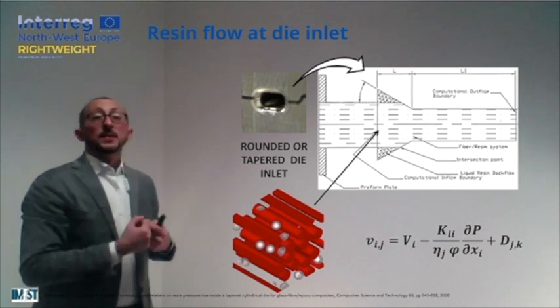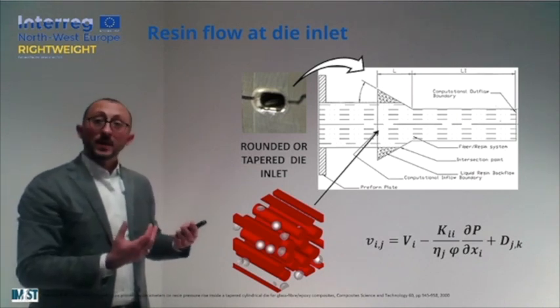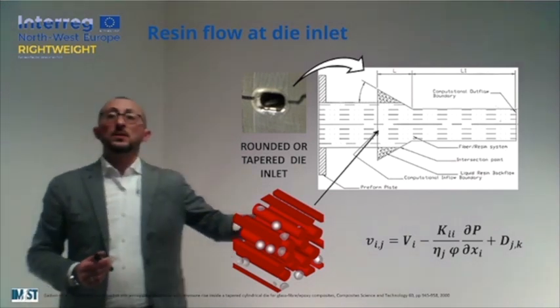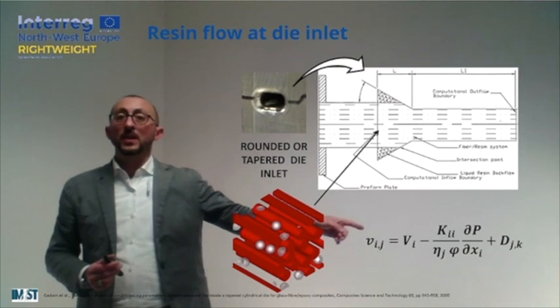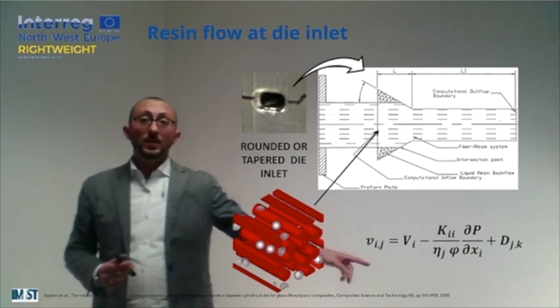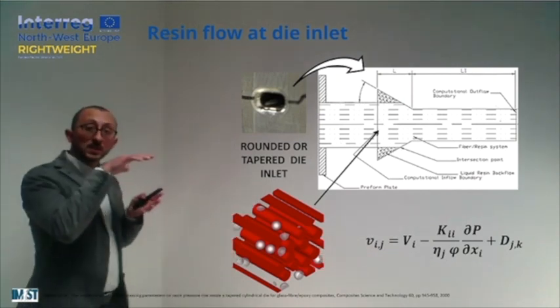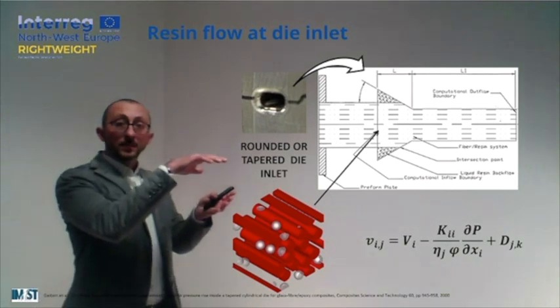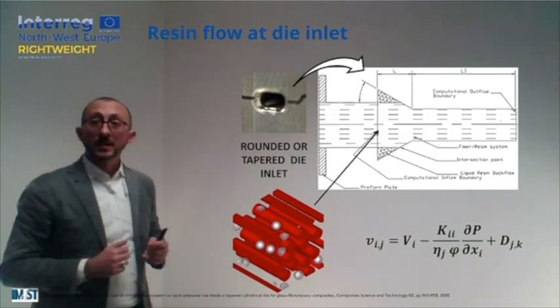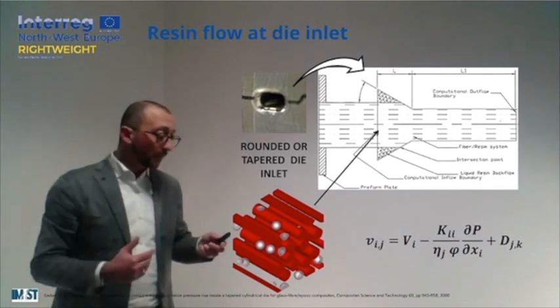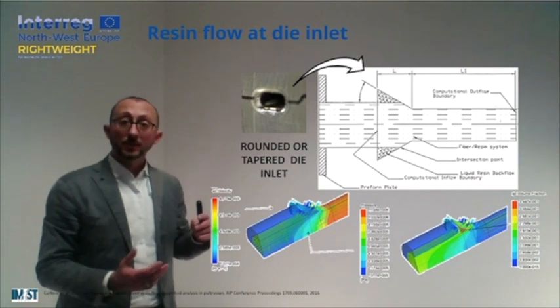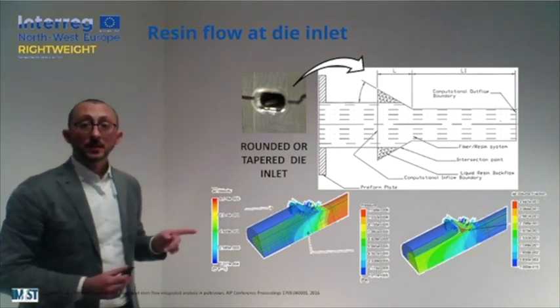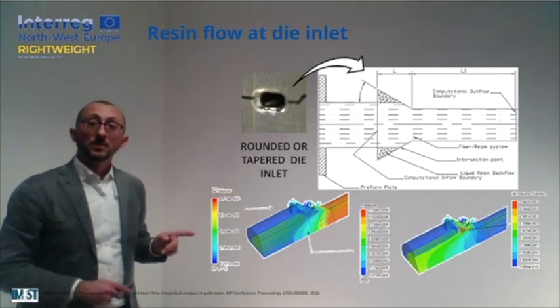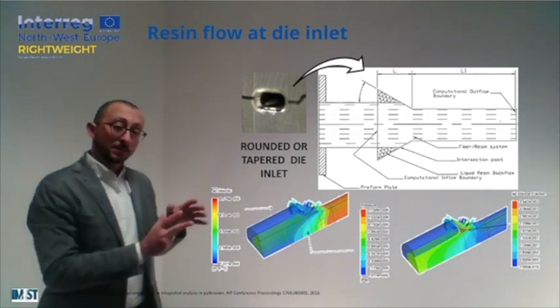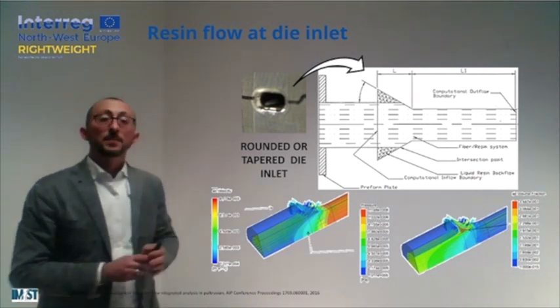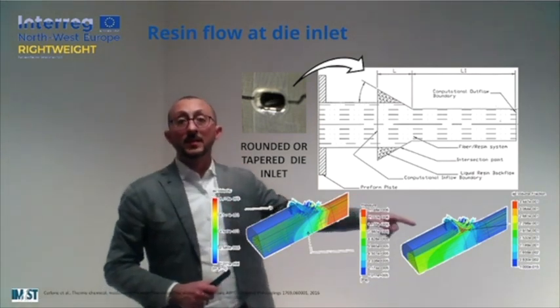And in this case, the resin flow and the air flow can be described and studied using the model that is depicted there. So a modification of the Darcy law, including also the velocity of the porous media. So this medium is traveling, and when the conical surface of the die is met at the intersection point, what we will have is some kind of compaction, an increase in pressure that you can see here, looking at these results from numerical simulations. And this pressure field pushes the air away from the cross-section, sending the air back.